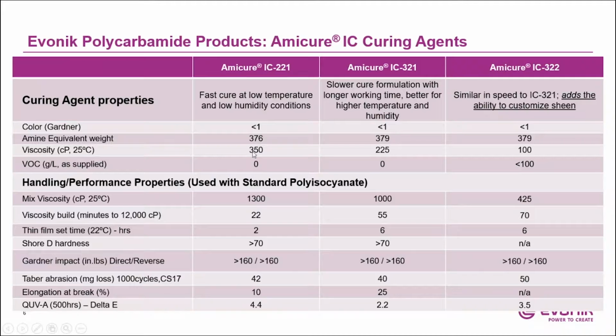The viscosity at room temperature is really low. So these are all below 350 centipoise. So the benefit there is it allows you to formulate a solvent-free coating. And as you see with the VOC as supplied, these have low or no VOCs in terms of 221 and 321. IC322 does have less than 100 grams per liter VOC, and that's coming in from the modifier that's used in the curing agent. However, that modifier does not have any odor, so you are able to apply it, and there will be no odor with the coating.